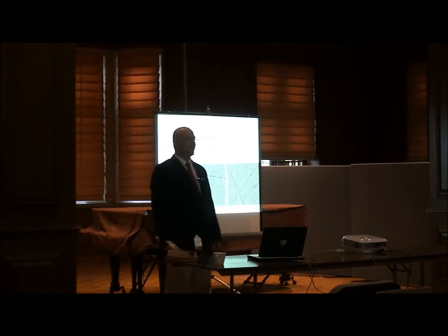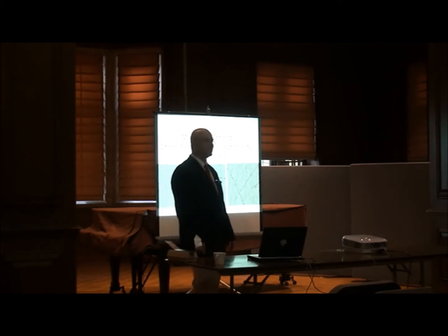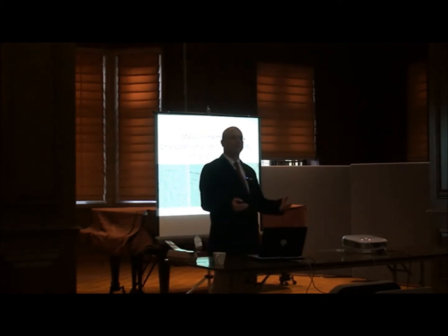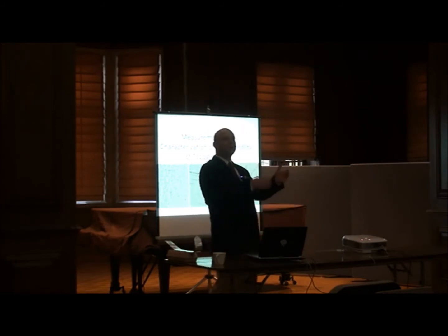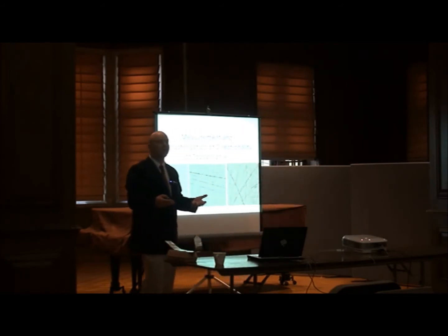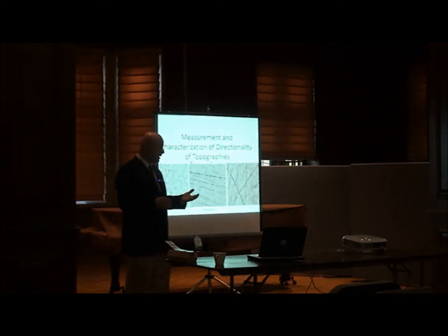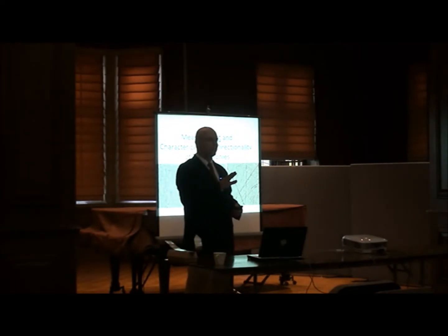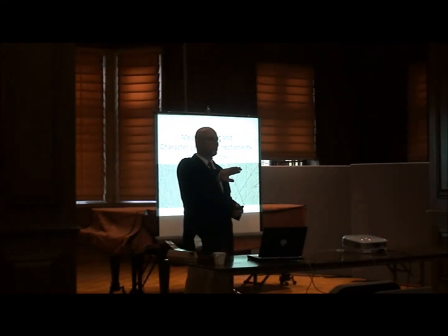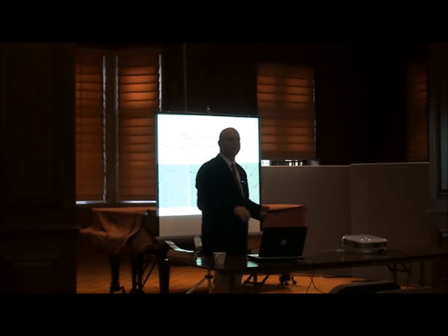So we did tests, and we did tests. And we said, well, the pavement probably wasn't isotropic. It probably was anisotropic. If you look at the nature of how the asphalt pavement is made, it's made by a machine that moves along in a direction. So there probably is direction in that surface. Whether or not it's important to you is different. But sure enough, if we took any surface and we turned it 90 degrees in software, we got different results for the analysis method that shouldn't care about the direction on the surface.